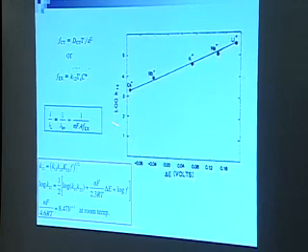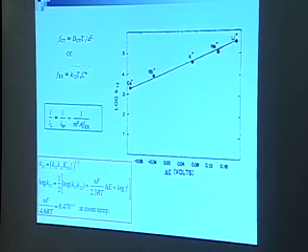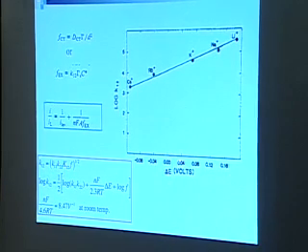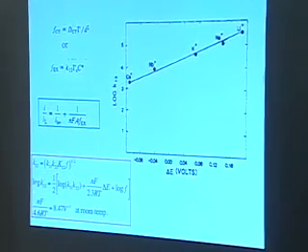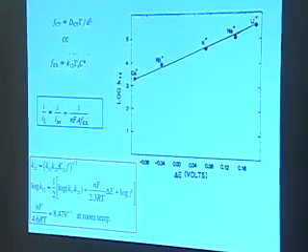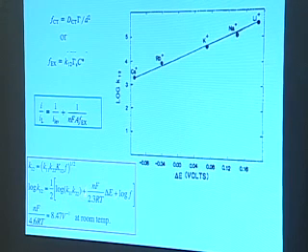A linear relationship, there's the equation I gave you the other day. K12 equals the self-exchange rate constant times the equilibrium constant, which is really that delta E right there, times this F, square root. So log of K12 should be equal to this thing right here, where if you take all these constants and throw them together, it's 8.5 per volt. That slope is 8.49.